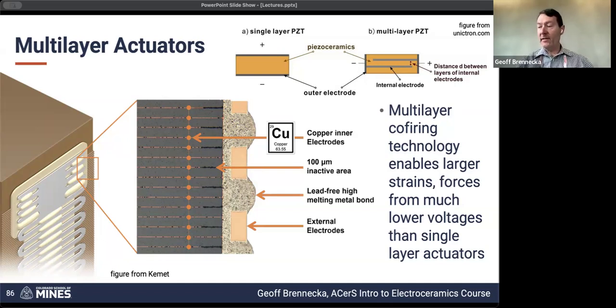We're going to get into why this ends up being valuable from a piezoelectric application perspective in a little bit. The short answer is that if you've got a single layer and you apply a voltage across it, the amount of strain that you get. So piezoelectricity is apply a voltage, apply a field, and get a strain. The amount of strain that you get from that is directly related to the amount of voltage you applied. Well, what if I want the same amount of strain but at a lower voltage? I can do that by making these multi-layer structures so that the field that's applied can be the same because it's across a thinner layer.